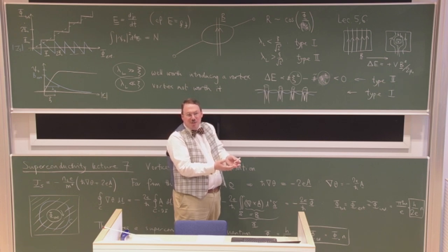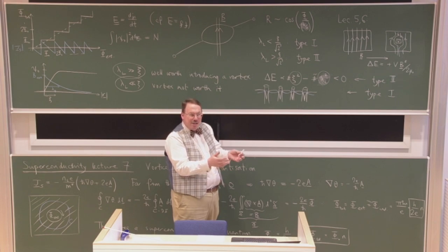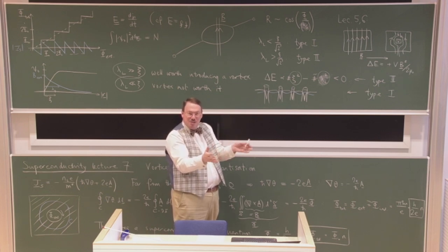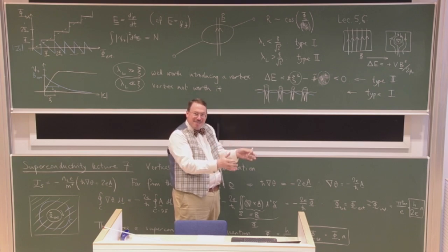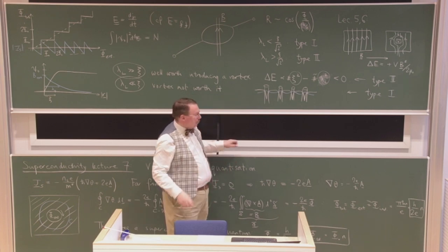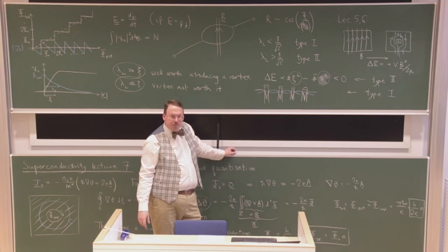chooses to do in the center of the vortex may be quite a delicate question and may depend on free energy effects from how well your normal state interfaces with the edge of the vortex, not just the sort of bulk free energy. And you certainly do sometimes pick up non-standard phases. There's a spin density wave and probably a charge density wave as well to be found in cuprate vortex cores,